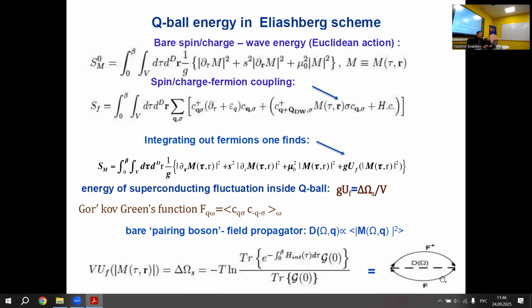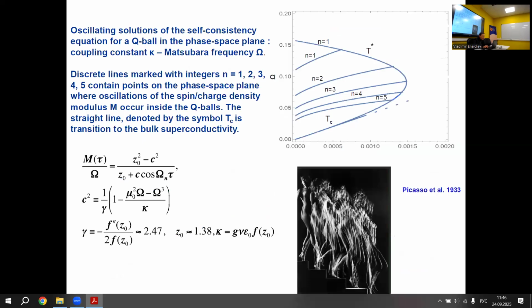There is some special trick. If you introduce some coefficient alpha, which ranges from 0 to 1, into the interaction Hamiltonian, you can differentiate this free energy over this parameter alpha, then calculate to all orders the first derivative over alpha, and then integrate over alpha back and you get the complete contribution. So this is what was done.